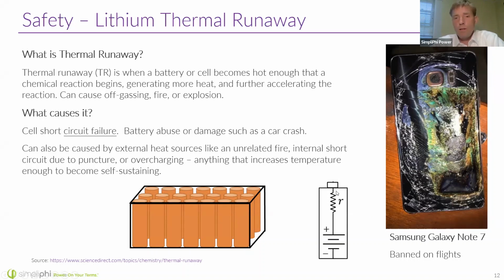All lithium-ion cells have a pressure valve in the top. If the battery gets too hot, too much pressure builds up inside the battery, and just like water can boil, the solvent can boil and turn into a vapor. And so that pressure is released out the top of the battery cell. Thermal runaway is when one battery starts going into a cycle like that. Again, this is very rare, but it can happen, especially in cases where you have extreme damage to batteries, like